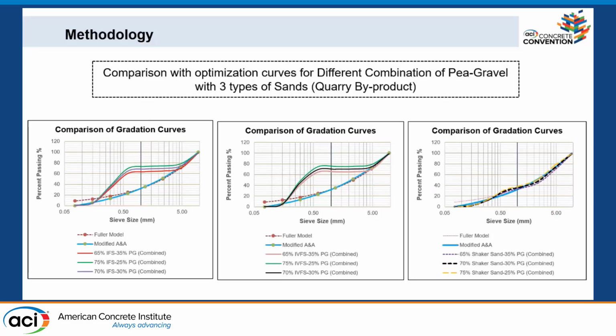So here we can see the comparison with optimization curves for different combinations of pea gravel with 3 types of sands. We have compared all our sieve sizes for the sands, the Quarry sands and the pea gravel with the combination of Fuller and Thompson curve and the modified Anderson model. We have taken into evaluation 65% of each sand and 35% of the pea gravel, that is the coarse aggregates, and we have ranged it to like 70% and 75% and vice versa.